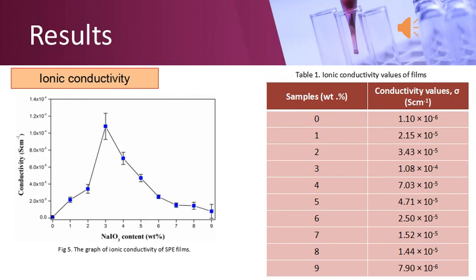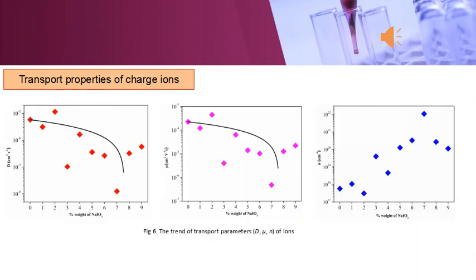So in general, it is observed that the ionic conductivity of the SPE film is related to the number and also the mobility of ions. The transport parameters play an important role in explaining the charge transfer and the ionic transport process in materials. The fundamental parameters are the diffusion coefficient, the mobility of the ions, and the number density of ions. Generally, according to Idris et al. 2009, the ionic conductivity in SPE film is related to the number and mobility of ions. However, in this study, the diffusion coefficient and mobility give a more significant contribution to the conductivity of the SPE films compared to the number density.